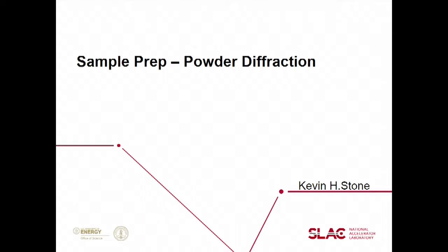There's a lot to consider in this, and I'm only going to go over a few parts of it. For a lot of things where you might be doing powder diffraction, you actually have essentially zero control over how you prepare the sample for the measurement, because the sample itself dictates a lot of how you have to prepare this. So if you think about something like a thin film that you're trying to grow, or if you want to watch an operando battery experiment, the preparation of the thing that you're scattering from is completely determined by making that thin film or by making an electrode for the battery that actually works. And so you really have minimal control over what you can do to get good diffraction data relative to what makes the sample do the thing that you want to study.